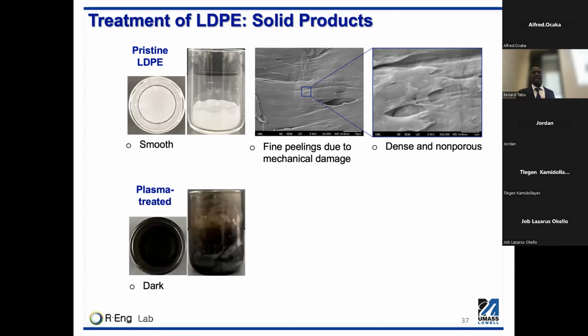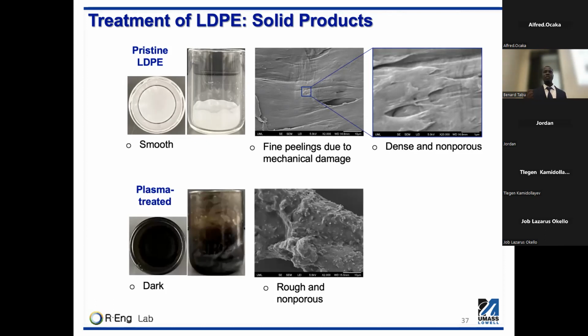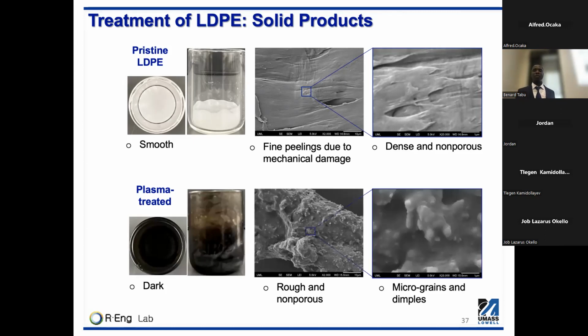So the treated low density polyethylene consists of a kind of embedded grains, and that was really also very interesting to us. And when we zoom in more, we see that these are actually grains which consist of dimple-like structures, and this is interesting.